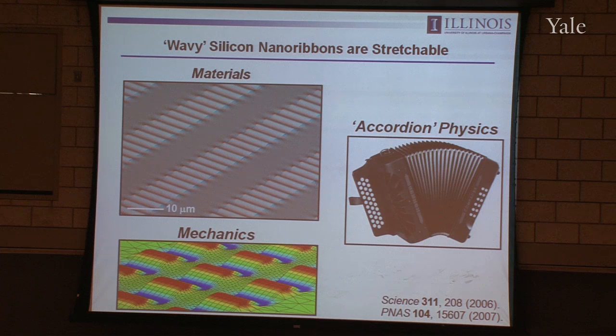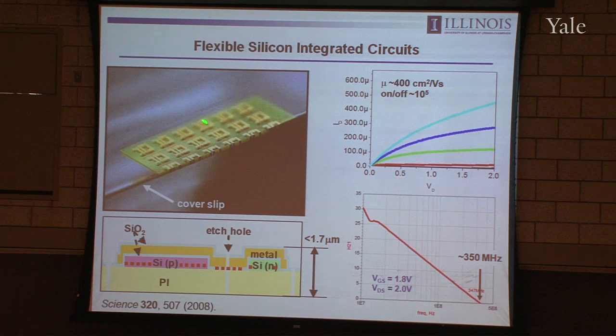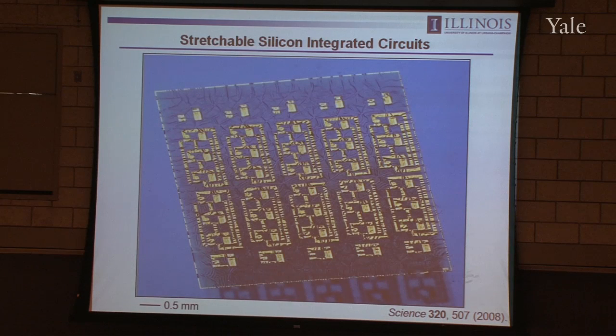But the same idea can be applied chip scale. So take an optimized ultra-thin integrated circuit like this, bond it against a biaxially pre-strained piece of rubber, relax the biaxial pre-strain, and now you get a kind of a 2D buckling pattern that forms. It's a lot more complicated than what I showed you before, but conceptually it's very similar.